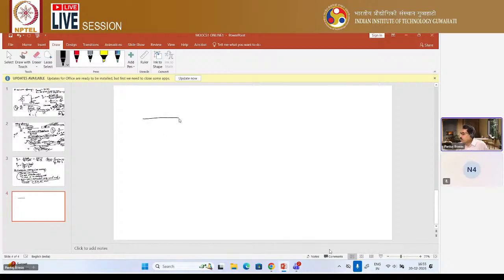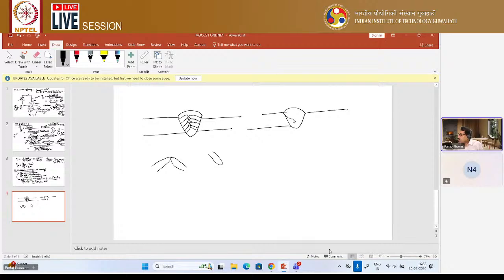What we observe is that once you do the welding, generally your weld material has columnar grains, which start from the boundary of the solid material. This type of grain growth has a name: it is called epitaxial grain growth. Sometimes this columnar grain can grow this way, and sometimes this columnar grain can grow in the downward direction also. That means in some cases your grain orientation can be like this. This type of phenomenon can be there, in the downward direction.